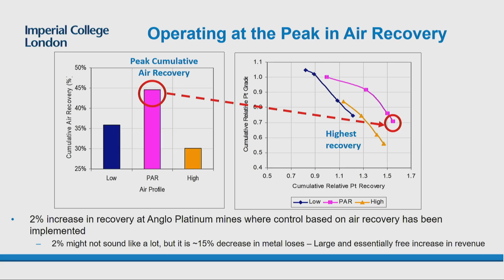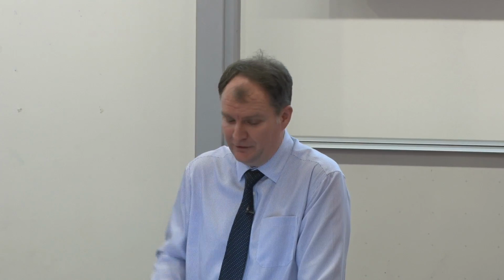As you increase the air rate, the air recovery increases and then decreases. This wasn't actually expected behavior. It was expected to either monotonically increase or asymptote to a value, but it does actually go through a maximum on pretty much every plant that it was measured at, and this maximum corresponds to a maximum in performance. So these plants perform the best when they're near this peak in air recovery, and so this has now been used as the basis for a control algorithm for controlling flotation cells in Anglo-platinum mines,